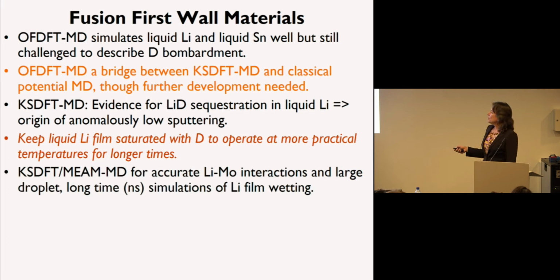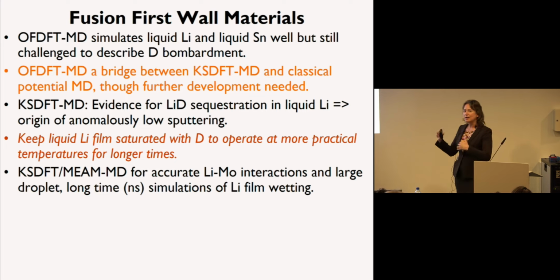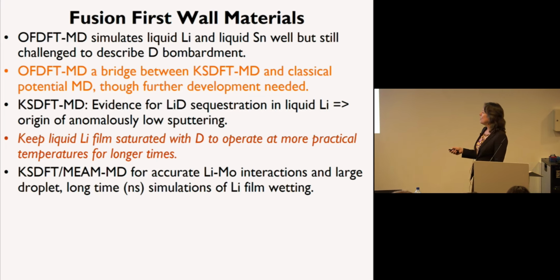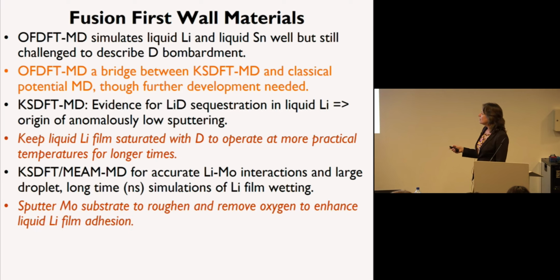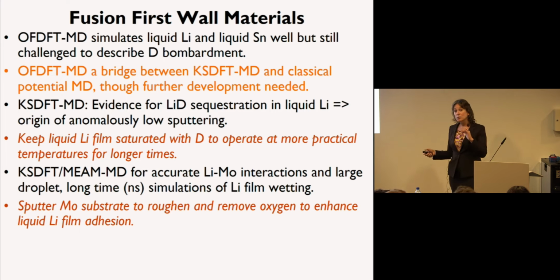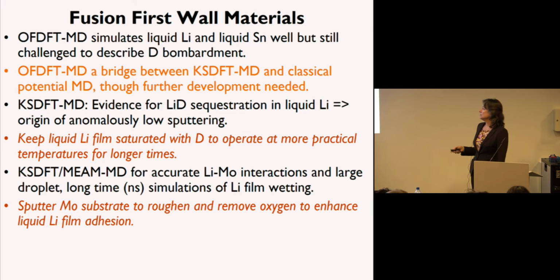I also showed you that we can get quite good results. I didn't show you the thermal desorption, but we can accurately simulate thermal desorption for the binding of lithium to molybdenum, and then we look at a droplet simulation, a fairly large droplet, and how it wets under long time scale simulations for lithium film wetting. What all of that work led to is our understanding that you'd like to have a rough substrate, to have it bind stronger and to remove impurities, especially oxygen, to enhance the film adhesion.